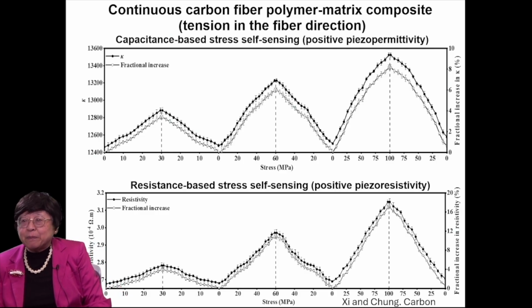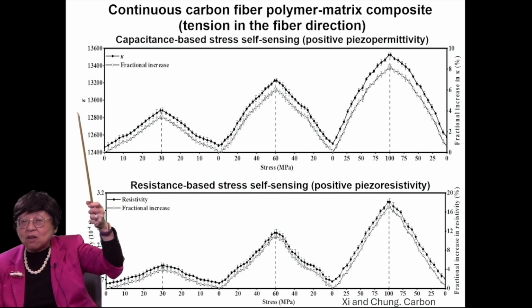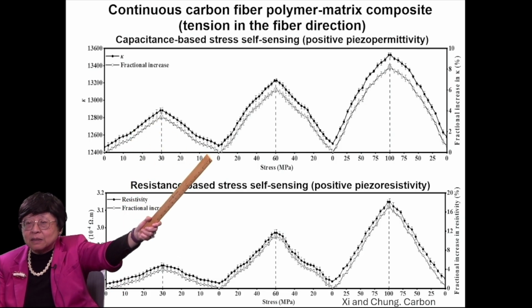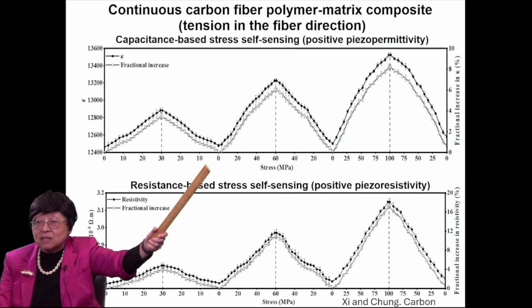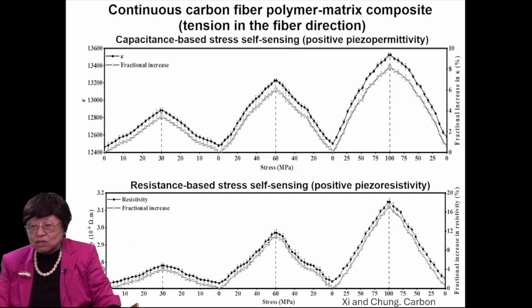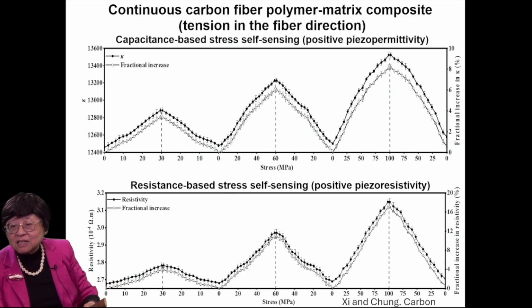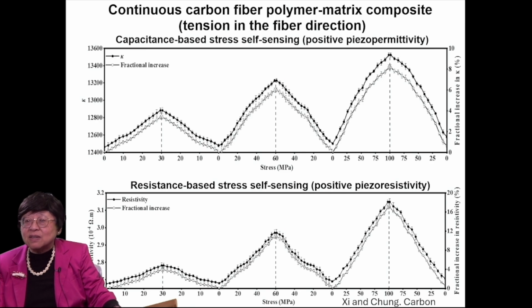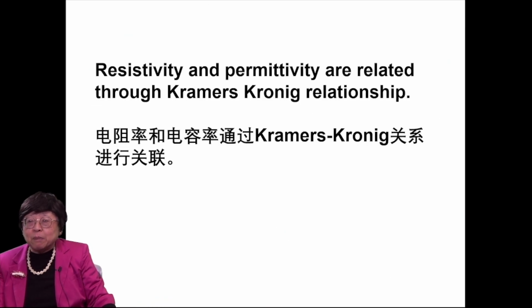Here's continuous carbon fiber polymer matrix composite with tension in the fiber direction. And up here is the relative permittivity, which I call kappa, during a tension application, 3 cycles of loading at progressively increasing stress amplitude. And you can see that the relative permittivity increases quite reversibly every time one applies tension. And that is a positive piezopermittivity. At the same time, we can measure the resistivity. The resistivity also increases reversibly every time one tensions, and that is positive piezoresistivity. In general, the resistivity and permittivity are related through the Kramers-Kronig relationship.